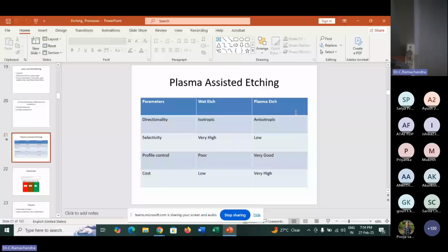Selectivity, it is very high in wet etch, but compared to this it is low. Compared to wet etch, plasma etch selectivity is not very high. So that is a bit of a limitation of plasma etch. Profile control: in wet etch I cannot control the etch profile. It is isotropic, it etches in all directions. But here, by tuning the process parameters, I can control the profile the way I want it. And cost, it is definitely low for wet etch. Any academic institute, any R&D lab can easily set up this facility. Plasma is quite high compared to this one, definitely 10 to 100 times more than this one.